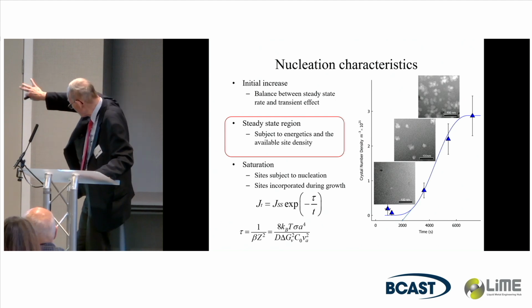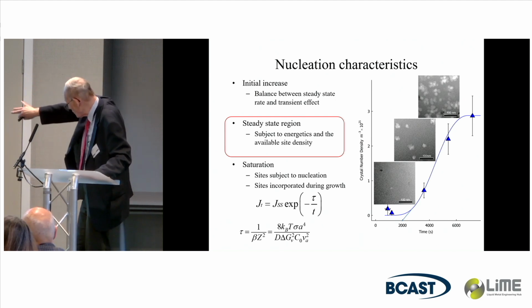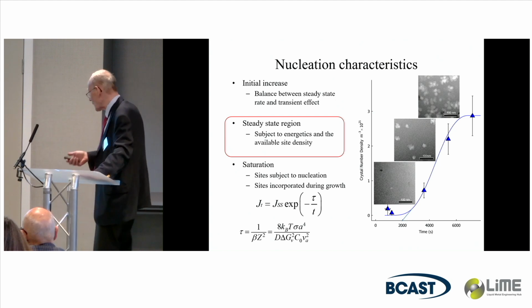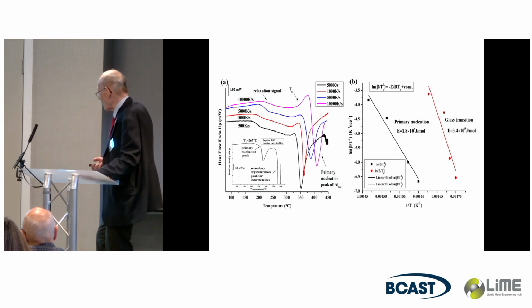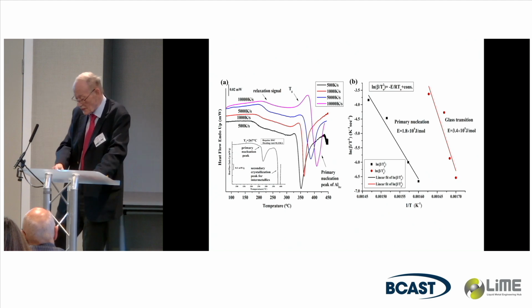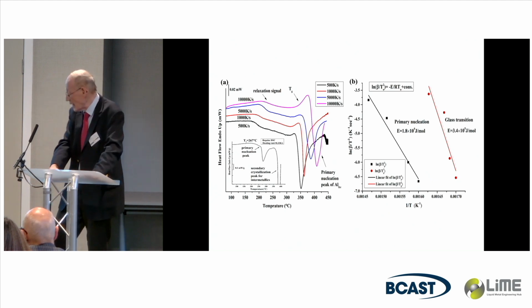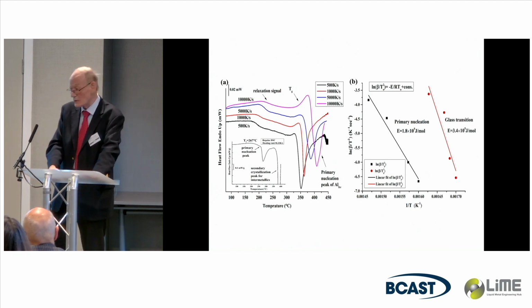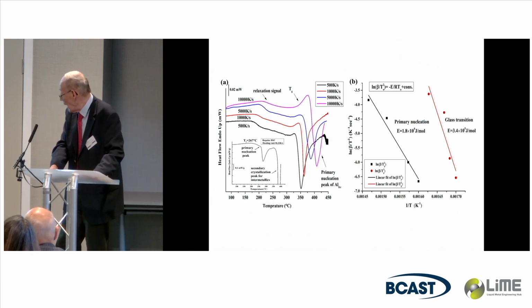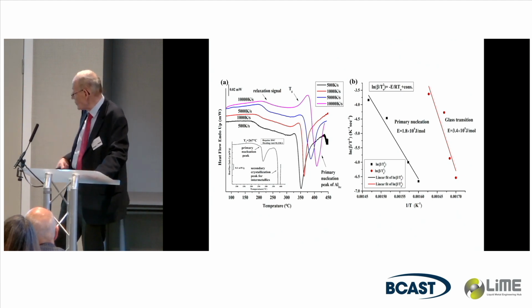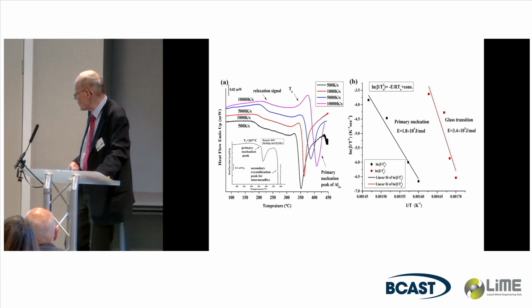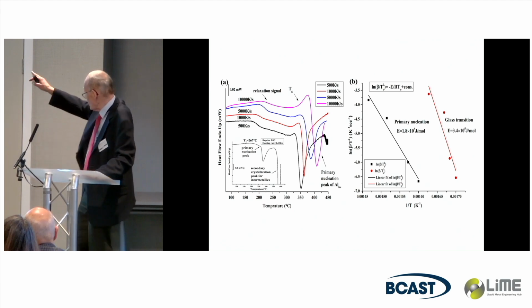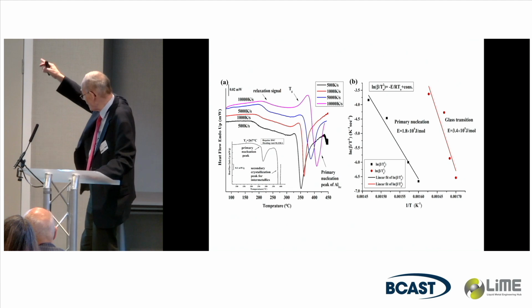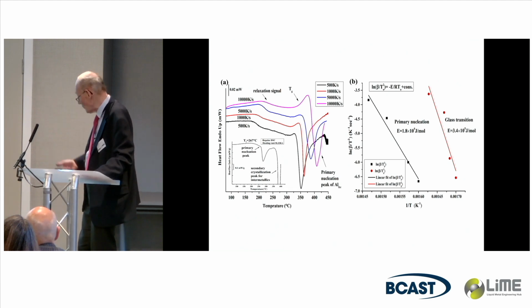Well, you can extrapolate the linear portion, but that's kind of uncertain. So we used nanocrystallization studies in a nanocalorimeter. Mettler produces this flash DSC. And by going at higher heating rates, you can build up the glass transition very nicely. And you could see that the Kissinger plot of glass transition versus primary crystallization allows us to separate the two.